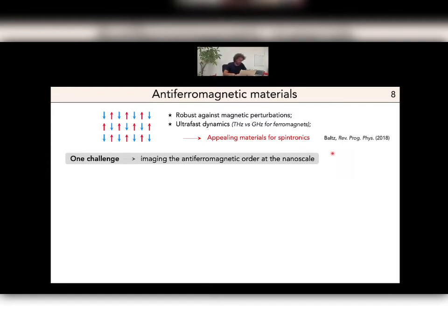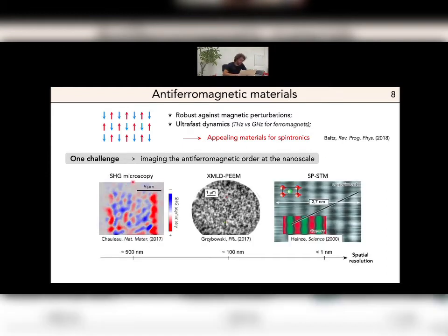There are a few tools that you can use. The first one is advanced magneto-optical microscopy, for example second harmonic generation, where you can image some antiferromagnetic domains, but the spatial resolution is still limited by diffraction, so let's say the micron scale. To improve the resolution, you can rely on X-ray imaging and bring the spatial resolution down to a few tens of nanometers. And if you really want to reach atomic-scale resolution, you can use spin-polarized STM, where you can see an antiferromagnetic order with a resolution below 1 nanometer. This is a really nice instrument. However, it's restricted to UHV conditions, and you also need a conducting sample to operate the STM.